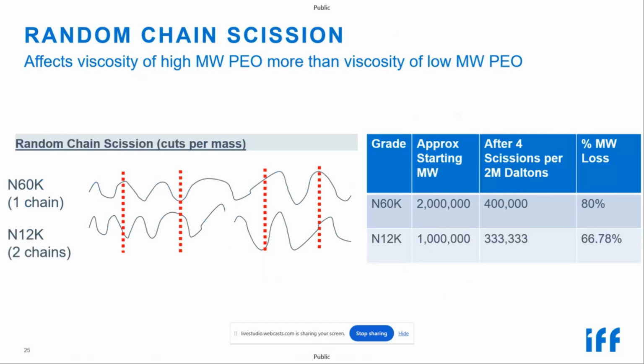So you can see how that loss impacts the higher molecular weight more so than the lower molecular weight. And the chain scission rate, we've been able to understand, is independent of molecular weight for the most part. So this is the assumption that you will see similar chain scissions per mass between the different grades. All right.